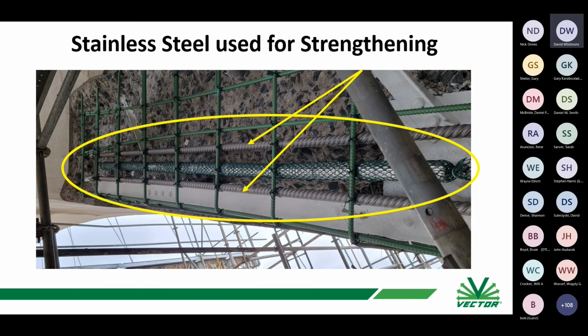I mean, here we have this giant anode sitting right next to stainless steel. Yeah. So a small amount of current from that anode is going to go to that steel. It's a very large, compared to your situation where you've got galvanized and a large mat of, let's say, stainless steel, you've got a different ratio of anode to cathode. The amount of zinc that's in that galvanizing is going to be really quite small compared to the total amount of zinc in those anodes. But yes, a certain amount of it will be consumed by going there, but it's relatively small.